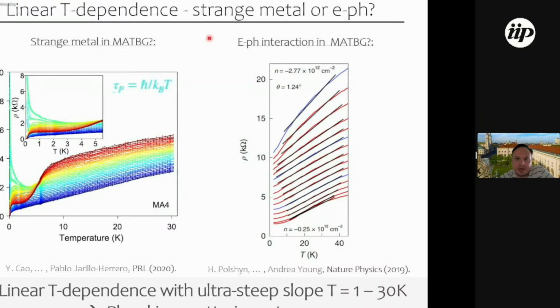However, immediately after that, the group of Andrea Young picked up on these results, and they explained that in graphene, in principle, linear temperature dependencies can exist. And these linear temperature dependencies can actually be just given by phonons. So in order to really settle the issue, to find much more evidence than was given before, we tried to first understand the governing principle of electron-phonon interaction in graphene, and also tried to create experiments where we can distinguish the two effects from one another.